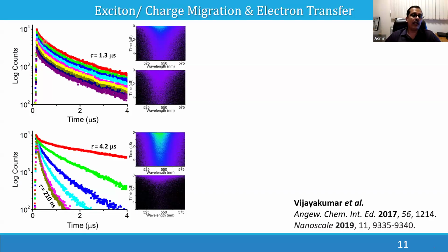Okay, so what you see is that with the increasing concentration, you will see a decrease in the intensity, but not the emission rate or the lifetime. Okay, so initially and finally the emission lifetime is the same because whatever is emitting, it is emitting just like normal, and whatever is quenched is completely quenched. But in the case of the film, it is very interesting. Though it has a lifetime of 1.3 microsecond in the solution, in the film state, because of excitation energy migration, the exciton is traveling from one side to the other side. It takes some time, and that time is getting reflected. Okay, that time delay is added up here, and the lifetime has increased from 1.3 microsecond to 4.2 microsecond.